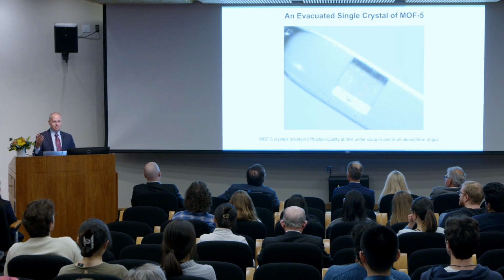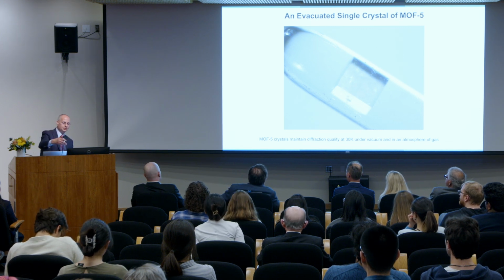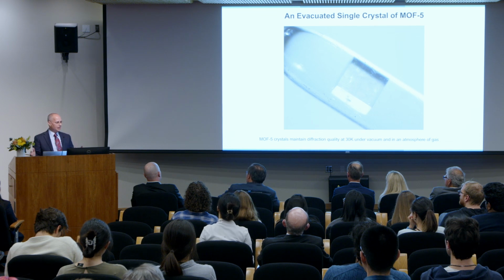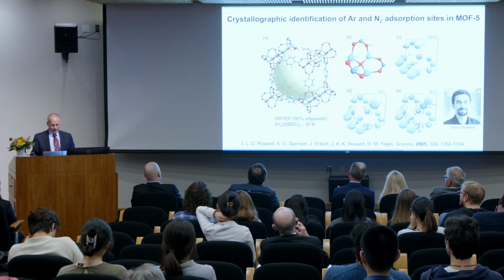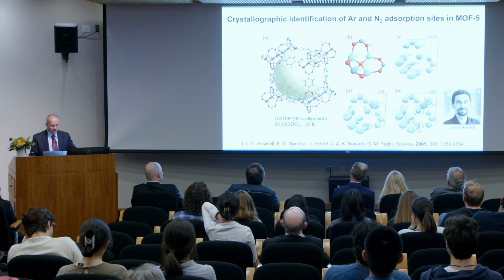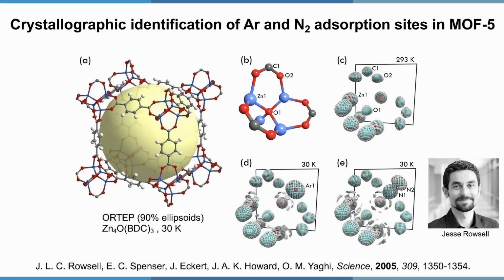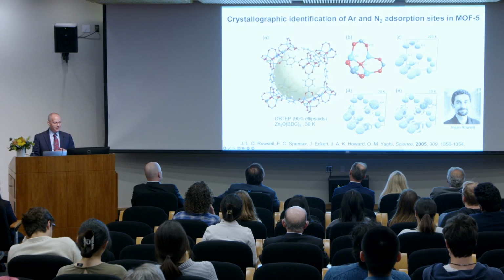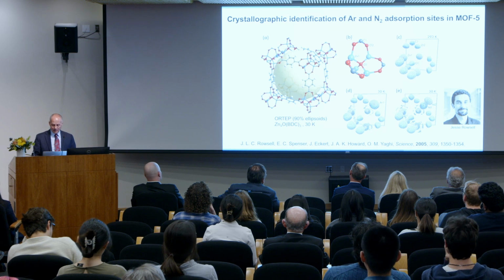The reason that's important is because you want to be able to capture CO2 and take it out without the structure collapsing. And so we proved back in 2005, beyond doubt, that an evacuated structure could be determined by single crystal X-ray, and that in fact it remains open in the absence of gas.